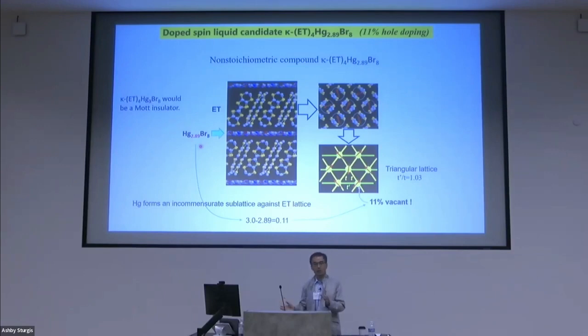with the structure. So in this case, the mercury has an incommensurate one-dimensional chain of the triangular lattice. If the content of the mercury is 3.00, it would be a Mott insulator, a half-filled Mott insulator. However, there's a missing content of 0.11, which contributes to the 11% hole doping. So this material is an 11% hole-doped system.